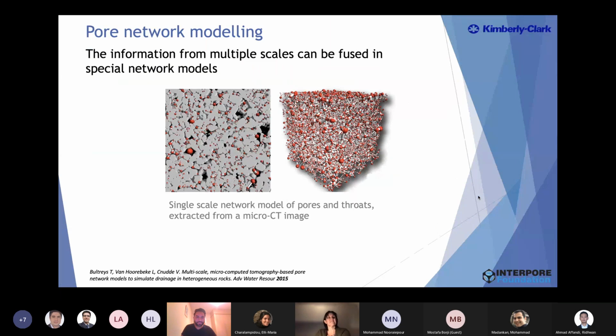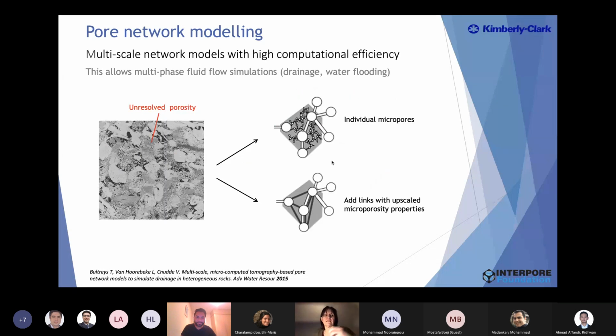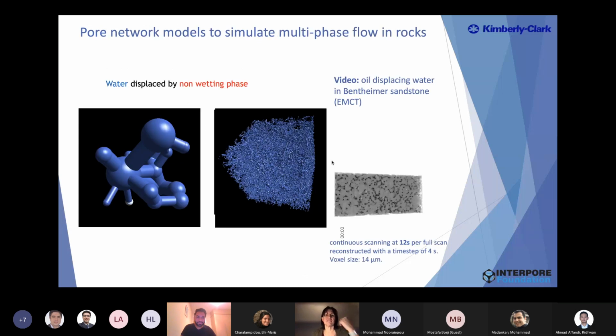And so one of the things is that CT can be used as an input for pore network models. I'm not a modeler, I'm more the experimentalist, but CT is important because it allows you to extract, for instance, the different pores and the pore throats extracted from micro CT. You can combine information of porosity that you have obtained with the different techniques at higher resolution and put this into one multi-scale pore network model, and then use this to, for instance, model behavior like water being displaced by a non-wetting phase. But you can also validate this by using dynamic imaging.